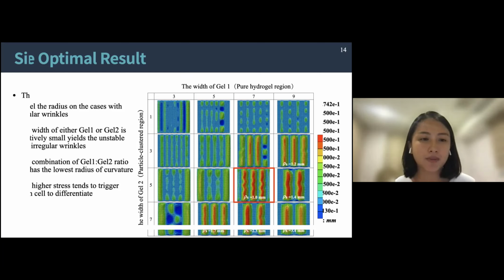So if the gel 1 is 3 or 5, or the gel 2 is 1 or 3, it will yield the unstable and irregular wrinkle, which is not considered as a good design when you use it as a stem cell substrate. Then we label the radius with the regular wrinkle patterns, and the pattern that has the ratio of 7 to 5 of the gel 1 to gel 2 has the smallest radius of curvature, which is corresponding to the highest stress, and it is the optimal design of the stem cell substrate.